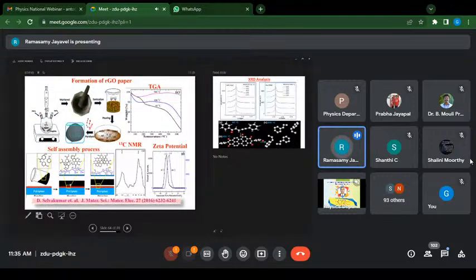And this was done by self-assembly process. You take graphene oxide and then make a slurry powder and then sonicate it to have a dispersion. And this dispersion is poured on a Petri dish, and the Petri dish is pre-coated with silane, so that it was easy to peel off after the formation of this kind of layered structures. And this was systematically done with all the studies.